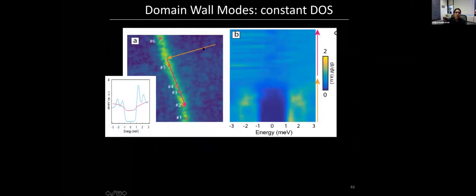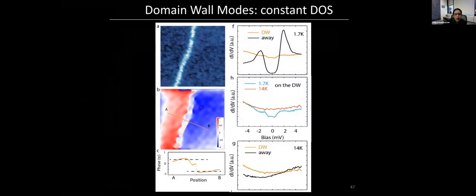So here is more data. This is a line cut, which goes this way and then this way. When you go in this direction, you see the nice superconducting gap, meaning the density of states is suppressed. And when you go along the domain wall, you see very featureless density of states inside the superconducting gap. Then you can increase temperature and make sure that this feature is associated with superconductivity. This is the spectrum on the domain wall showing the finite density of states. And if you go to high temperatures, which is 14 Kelvin above Tc, this entire feature disappears.